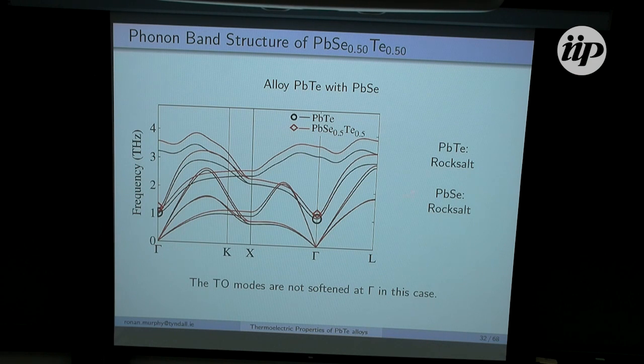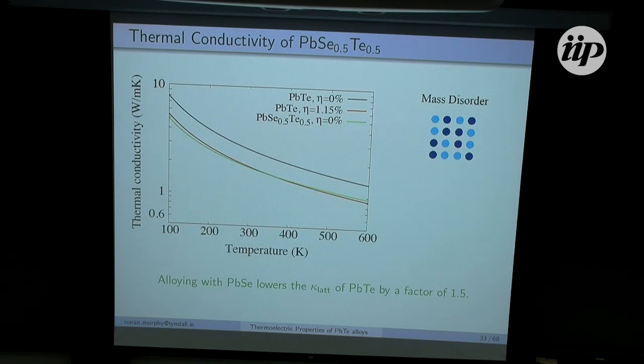Looking at the phonon band structures, we see there are a few differences, but this is largely due to the fact that the alloy and lead telluride have a different mass. Particularly, if we look at the frequency of the TO mode at the gamma point, you see that it's more or less the same. So by alloying, we haven't pushed it towards the phase transition, but we have introduced mass disorder.